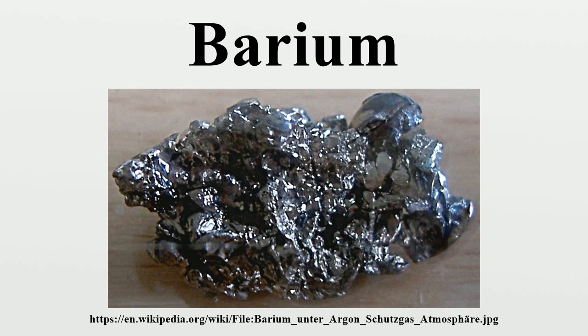Barium metal is produced by reduction with aluminium at 1100 degrees Celsius. The intermetallic compound BaAl4 is produced first. 3 BaO + 14 Al → 3 BaAl4 + Al2O3. It is an intermediate, which reacts with barium oxide to give the metal. Note that not all barium is reduced.